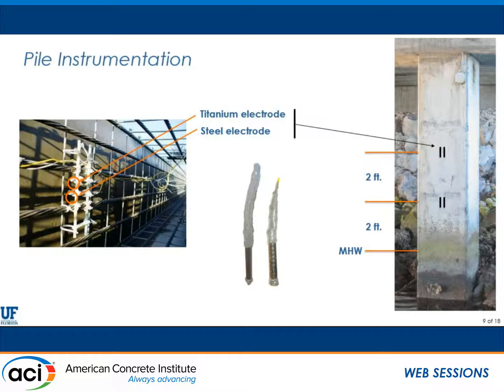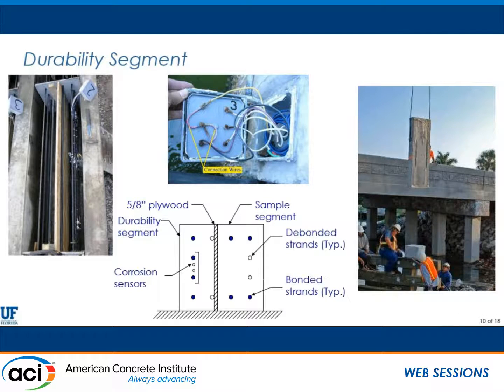Part of the problem with maintaining an exact height above mean high for our sensors is that the piles don't all get driven to the same elevation, right? So we actually anticipated that, believe it or not, and decided to add what we called a durability segment. While we were casting the piles in the pre-stressing form here, we subdivided a little short 4-foot section and cast a 6-inch thick or so piece of concrete using the same concrete and same pre-stressing steel that are in the piles. And then these are hung from the fender piles after the bridge was constructed.